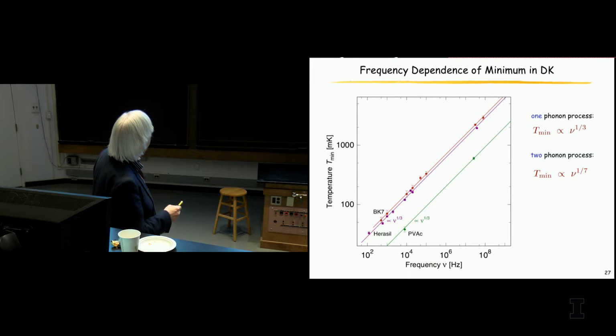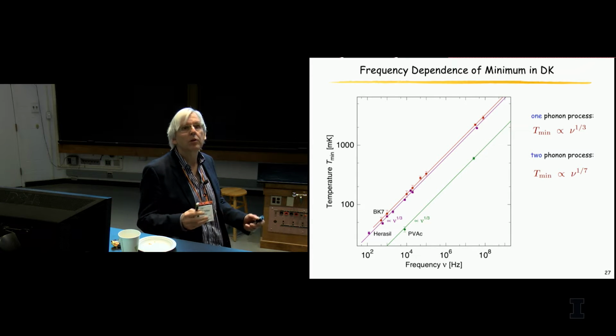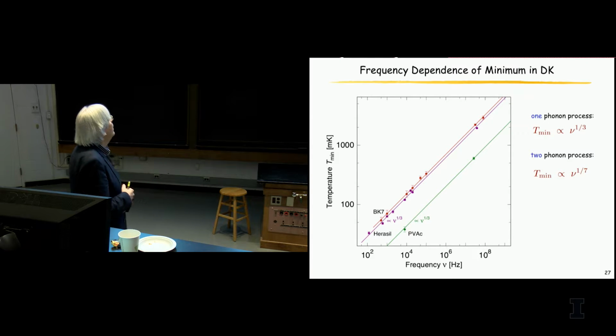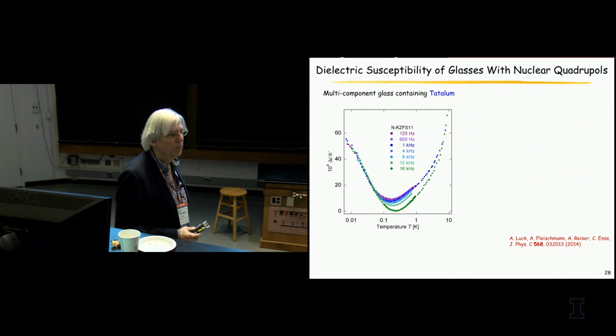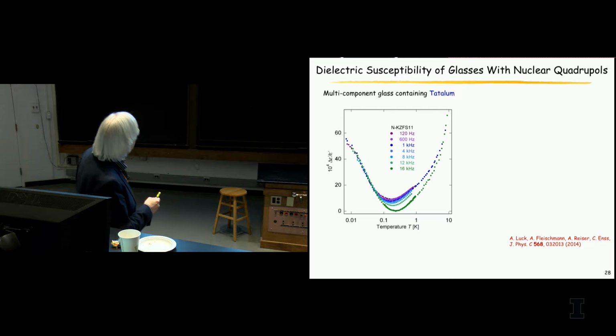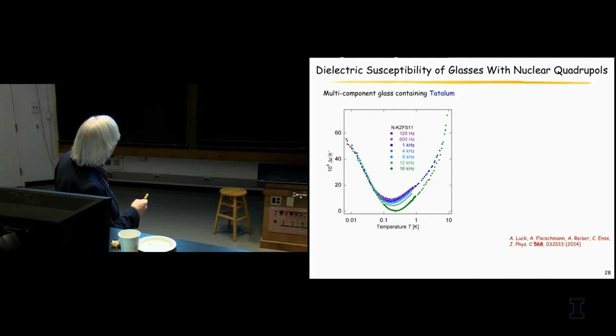It also tells you that the one phonon process really holds up to 2 Kelvin or something like that, which wasn't so clear for a long time. But then we turned to those systems with large quadrupole moments. And what you see here is at higher frequencies, there is still a smaller shift. This is with tantalum. So from 16 to 12, there is a small temperature shift. But then it stops doing that.